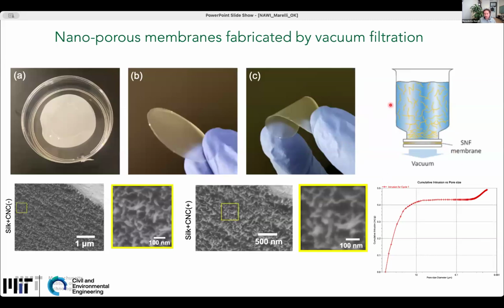So to make a long story short, we can grow these nanofibrils in water, then use vacuum filtration to compact them, and we end up with membranes of different thickness. We can go from hundreds of nanometers to several microns. These membranes are extremely robust mechanically because silk and nanocellulose are robust polymers. They're bendable, they are flexible, and they can be used to filter water by applying pressure to them.